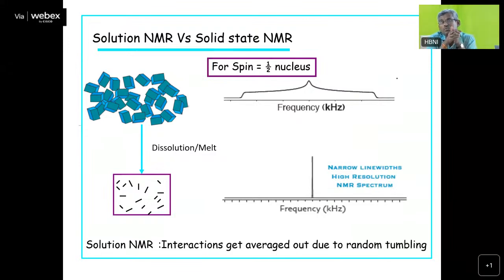Sodium 23 is an NMR active nucleus. As the near neighbors change so rapidly, the interaction between the ions gets averaged out, and there will be negligible interaction. Due to this, what we get is a very sharp line, a narrow line width. So you can get information on the environment around sodium. If you put sodium chloride in water, the sodium ion will be hydrated, and the hydrated sodium ion will be characterized by a very sharp line. But instead, rather than putting it in water, take sodium chloride and grind it very well.